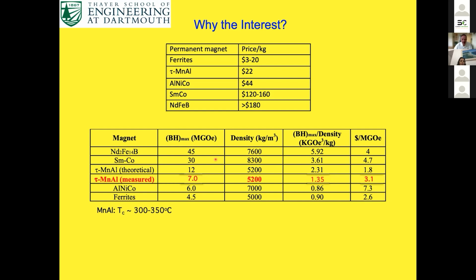7. Interestingly, if you take the energy product and divide it by the density, so you have a density compensated energy product, you can see the tau manganese aluminum actually does quite well, even better compared to some of these other materials. But if you look at the cost per unit energy product, you can see that for the theoretical value of tau manganese aluminum, then it actually has the lowest cost of any magnet. Currently, though, it's actually a little bit worse than ferrites because we've never reached that value.